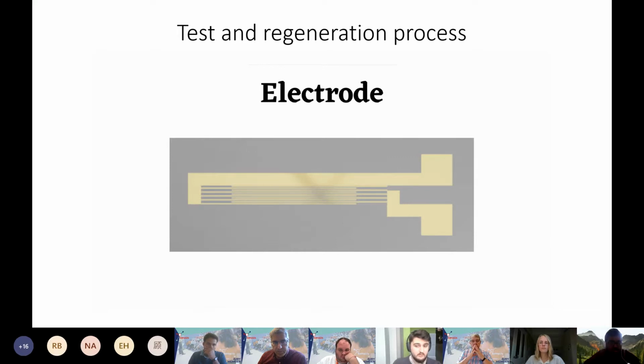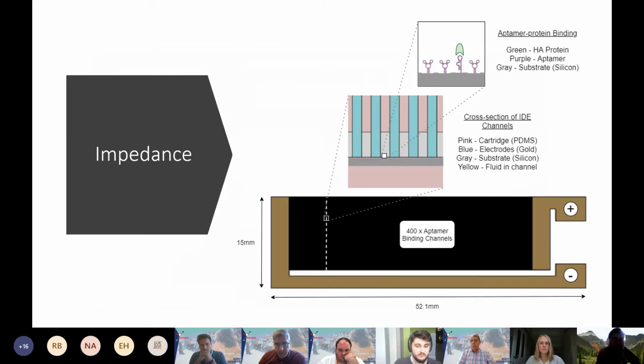For recycling, a hot water bath at 95 degrees is sufficient to denature the Aptamers, causing HA to be released from their complexes. The 7M urea wash then removes the unbound HA from the electrode. Finally, it is left for 15 minutes for the Aptamers to reform before the test cartridge can be reused. Our IDE contains 400 Aptamer binding channels as shown in this diagram here. Our EIS assay measures the difference in impedance across each channel caused by the presence of that captured HA against the reference impedance, or PBS.